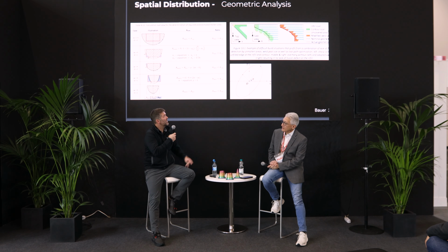And so we would be able to analyze that geometry, like I mentioned, and find the overhang angle. We can also determine the laser angle of incidence or deflection angle. That might be a further modification that you want to make. And once you determine the shape that you want, you use the model of melt pool shape that could come from one of the multi-physics models, and then choose where to apply the mark and then what parameters to use on that mark. And that is how you achieve that improved surface finish on the far right.